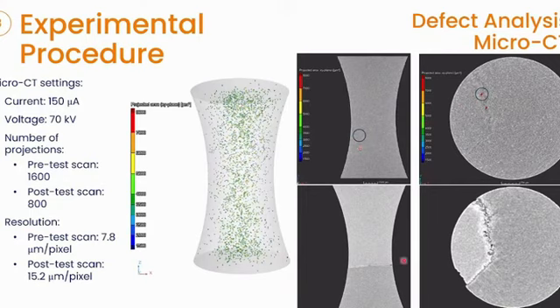And here at the bottom are the slices in the same positions of the overlapped pieces after the ultrasound test, showing that the fracture indeed passes over the identified defects. Incidentally, this one was next to another big defect, so it makes sense that the fracture passes through both of them.